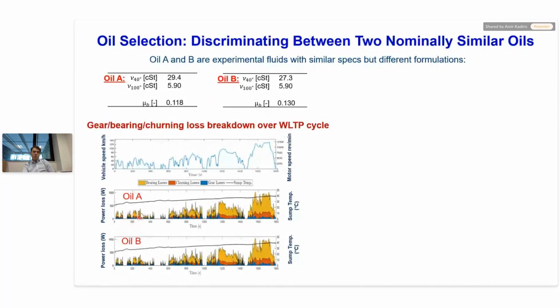Here you have the evolution of temperature, this black line, plotted on the right-hand side, and the individual losses. So in yellow, bearing loss, in orange, churning loss, and in blue, gear loss in an electric drive unit for that particular vehicle. And you can see how they evolve over time. You can see that the bearing losses dominate. At higher speeds, churning loss becomes significant. Gear losses as a proportion are less at higher speed, but at lower speed, gear losses are much bigger and churning loss is smaller. And this is for oil B.